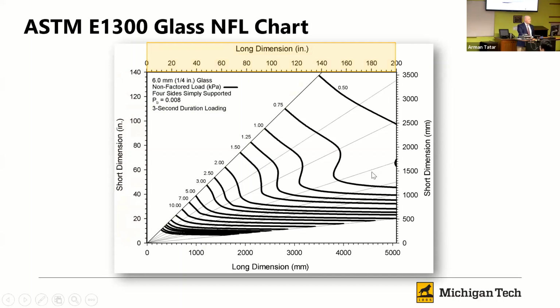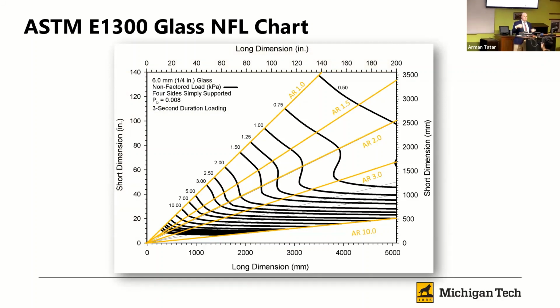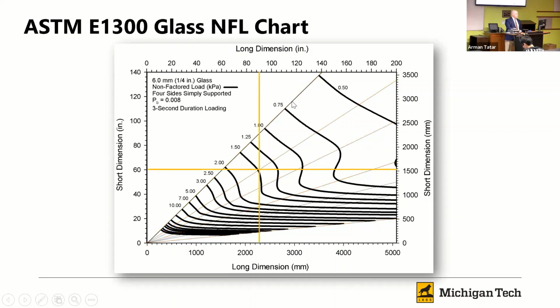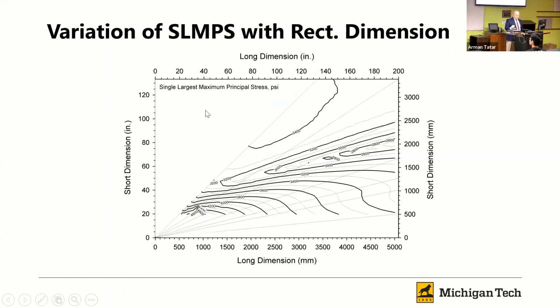This is a problem. Then we have these radial lines, which represent aspect ratios. What we can see is that the aspect ratio, or how square or rectangular our piece of glass is, impacts the strength of the glass. We also see that the area impacts the strength of glass. That's why, as we go to larger areas, the load, which is what these lines represent, becomes smaller, and if we have very small pieces of glass, those load lines get much larger. So if I want to design a piece of glass, say maybe a 90-inch by 60-inch piece, I figure out where those intersect, and we would find that we're sitting at about 1.5 kPa, which is about 31.5 PSF, pounds per square foot. With that, we would go on to modify for other factors. I'm going to come to that.